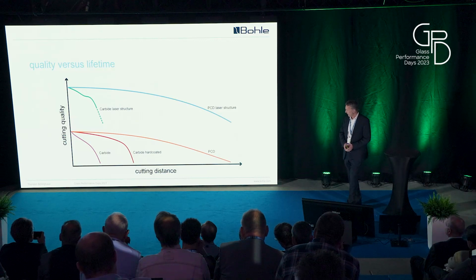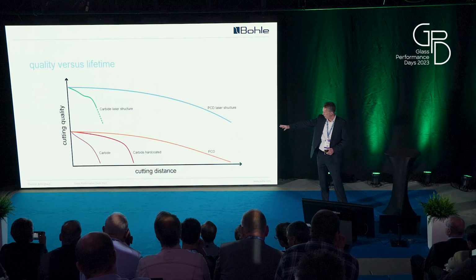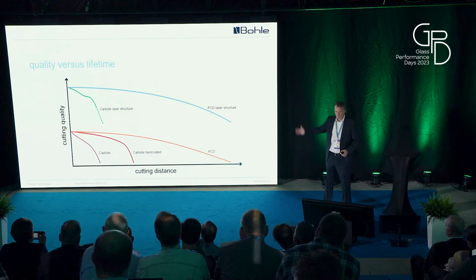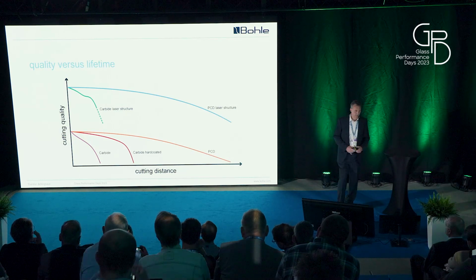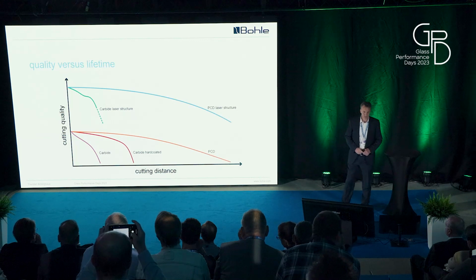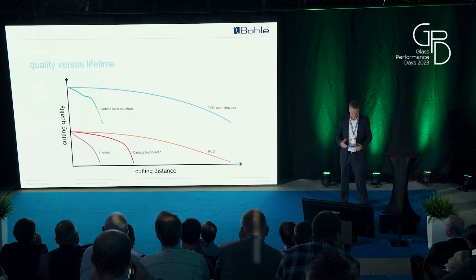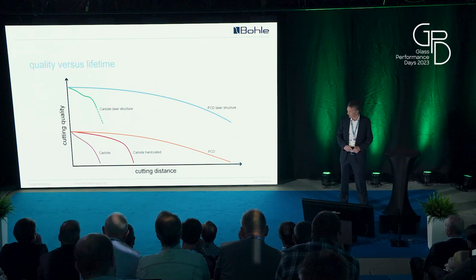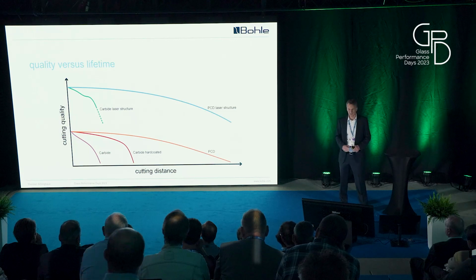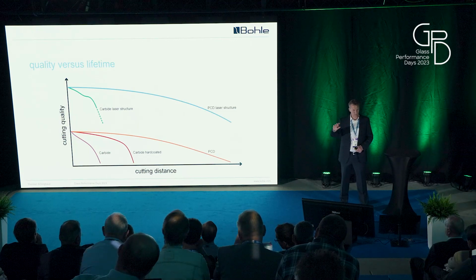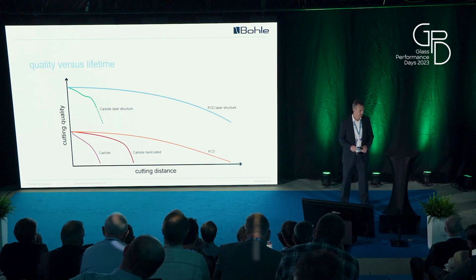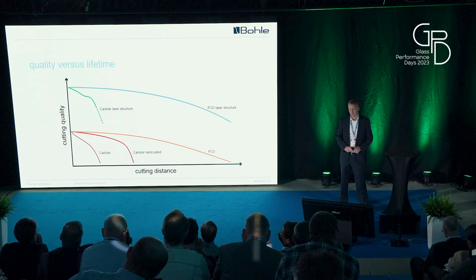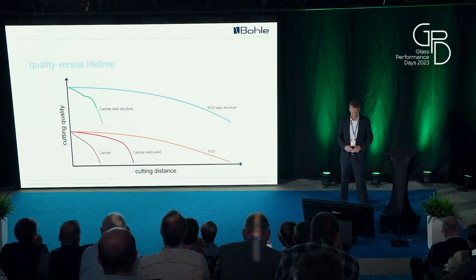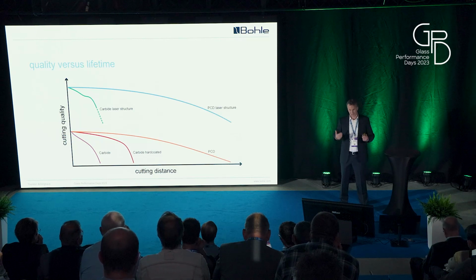And now if you look at the lower part, the carbide wheel has the wear and lifetime conditions and properties as they are. So if it goes down, it doesn't mean that you can't use it anymore. Normally in your process, you raise the cutting force or you adapt your parameters so that you compensate for this. But in the end, it wears and you have to counteract this.